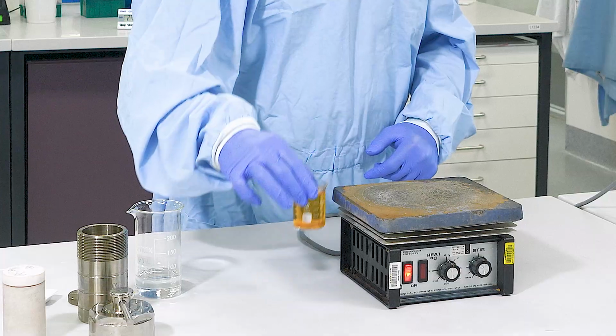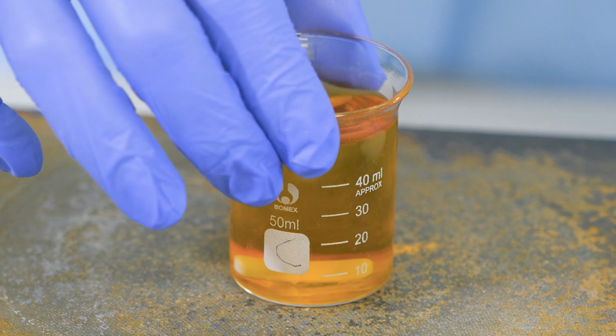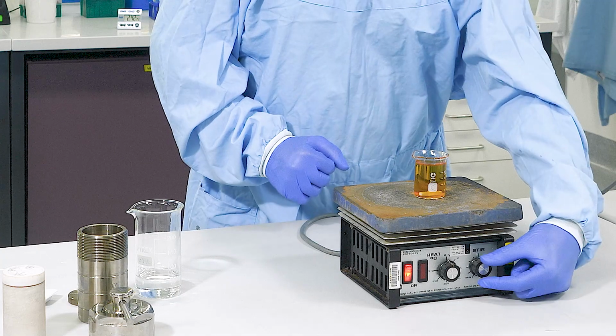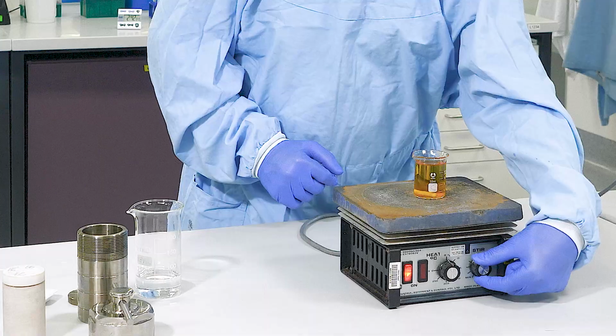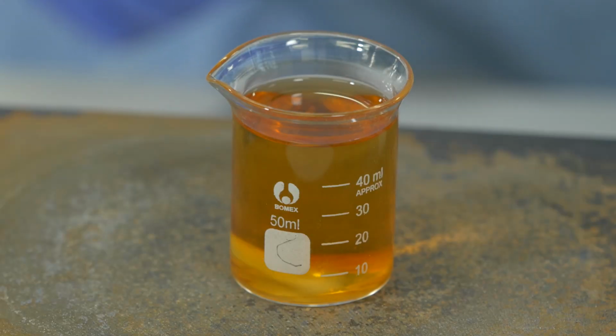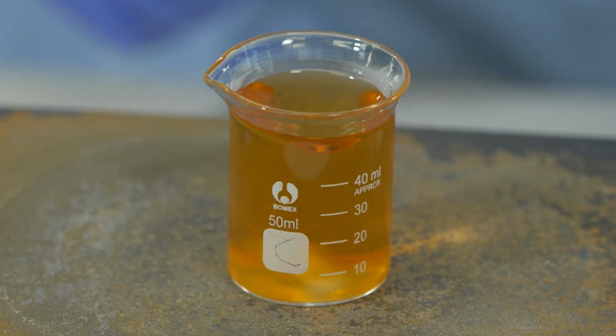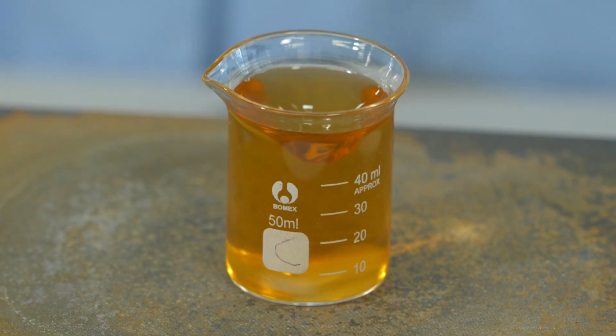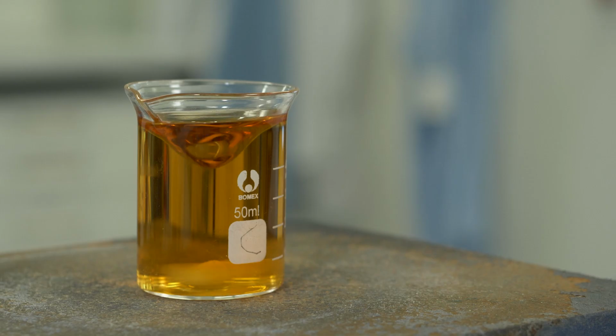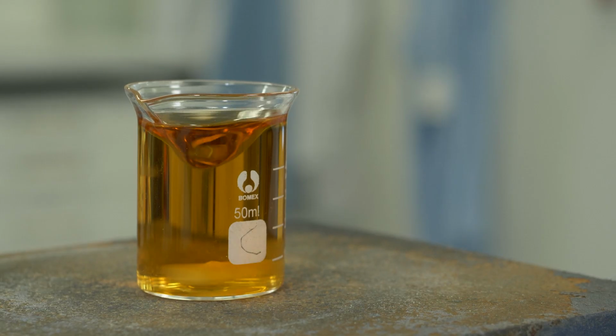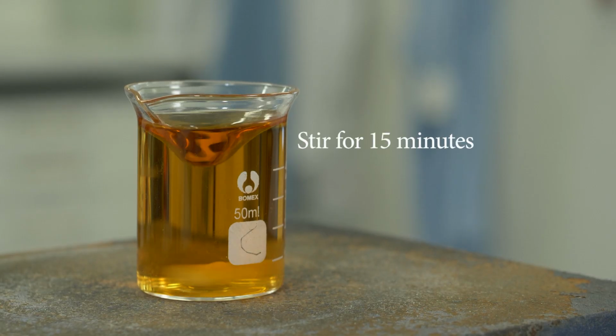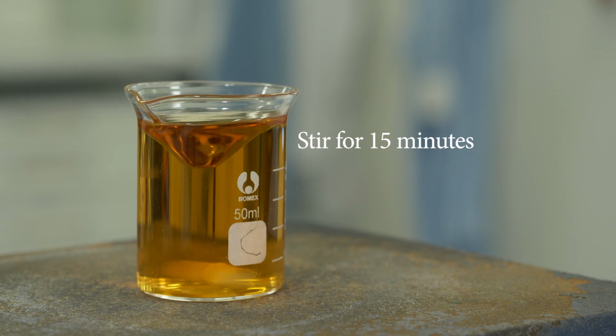Now I'm going to put this beaker on top of the plate and start stirring. I set the stirrer to 300 RPM and make sure the heat setting is off. Now we can see that the magnetic stirrer is spinning. We'll just leave it for 15 minutes until it mixes and we no longer see powder particles.